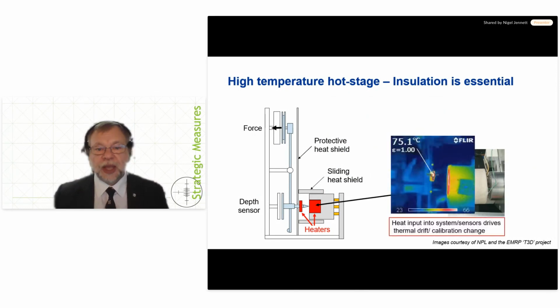The iterations of this stage got to the point where we had a sliding heat shield in order to stop the heat getting out, because if you don't have a heat shield, you've got something that goes up to several hundred degrees centigrade inside the environmental enclosure that you carefully bought to keep the lab temperature out at 23 degrees centigrade. So you've now got something that's pumping heat out into your very carefully controlled environment and will therefore cause potentially a lot of problems.